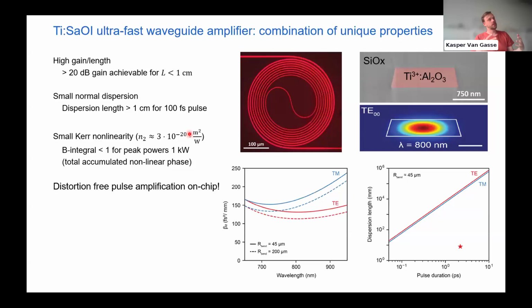So if you look into more detail at this tiny amplifier that we made, it's just an 8 millimeter titanium sapphire waveguide. And because of the properties of titanium sapphire crystal, you can still get quite some gain, about 20 dB, for something that's less than 1 centimeter. So that's really amazing. That's very hard to do, combined with this very big gain bandwidth.